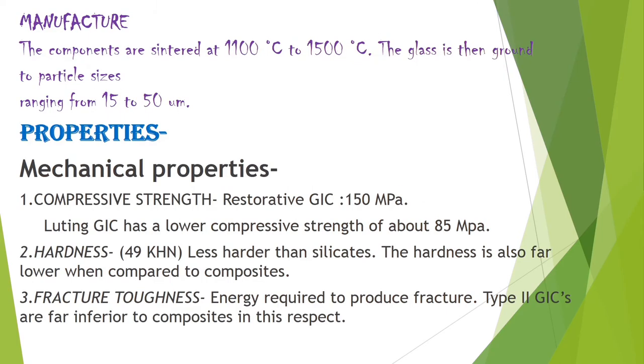Regarding manufacture: the components are sintered at 1100°C to 1500°C. The glass is then ground down to a particle size ranging from 15 to 50 micrometers.